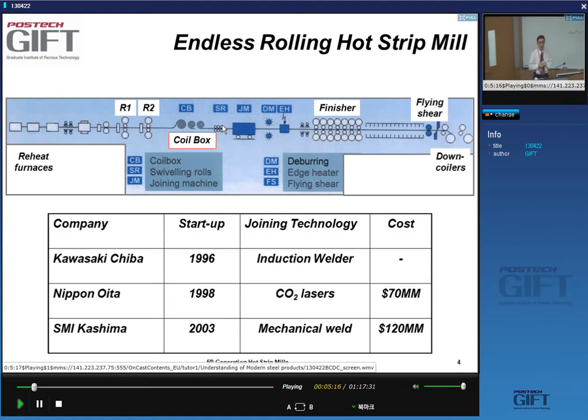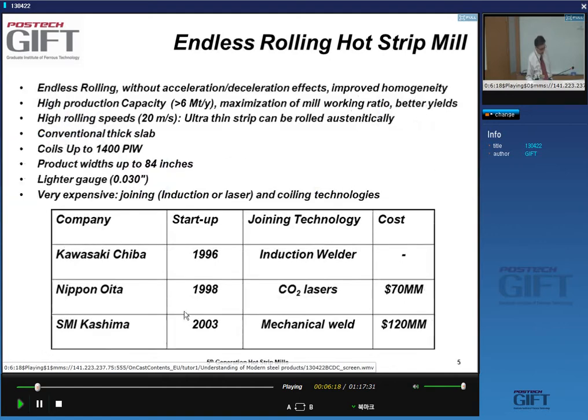And then obviously, there are not many places where you need high temperature welding. Usually you don't weld in these conditions. So the technology had basically to be invented, and there are different technologies: induction welding with lasers, mechanical welds. And obviously you can see that the investment costs and maintenance costs of such an endless hot rolling mill are very considerable. At the time, the only companies who were able to invest in this technology and develop it were Japanese companies who were doing very well at that time. I don't think that in the current situation these investments would have been possible.